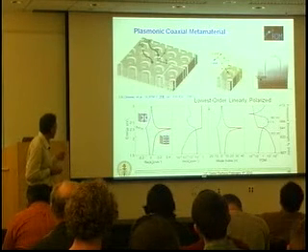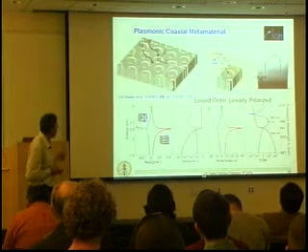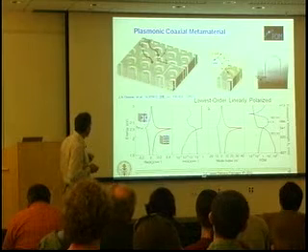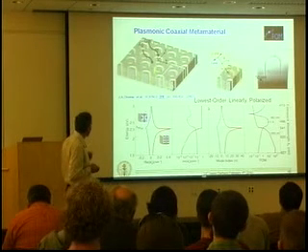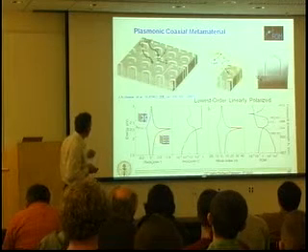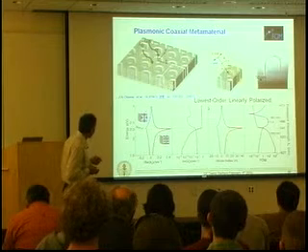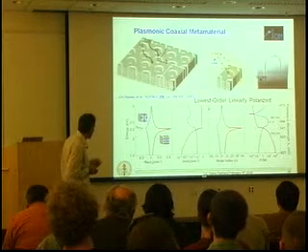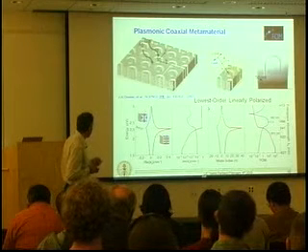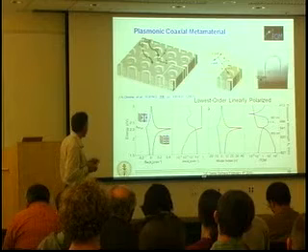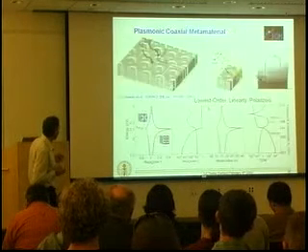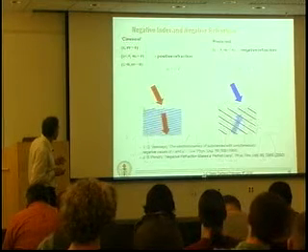This is an example of a negative refractive index material that we've been working on, a plasmonic coaxial metamaterial. It's a single thin film of silver, about 100 nanometers thick, where we cut air grooves and we can fill them up with dielectric. It helps to fill it with a high dielectric constant dielectric. But these can exhibit, for a band of frequencies in the visible range, negative index. It's not narrow, depends on your judgment. It's in the blue-green region. Moreover, it exhibits a broad angular acceptance for the negative index mode.